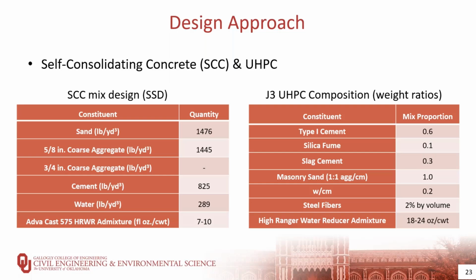In terms of the mix designs that we used for the concretes, the J3 UHPC mix design developed at the University of Oklahoma through funding by the Oklahoma Department of Transportation and ABC UTC was used in this study for the UHPC portion. The table here on the right shows the composition of J3 UHPC with a 2% steel fiber content by volume. The mix design on the left was used for casting the self-consolidating concrete, the SCC, portion of the girder specimens with an expected 28-day strength of 10,000 psi.